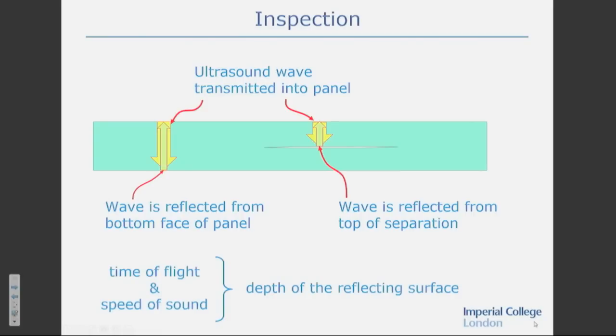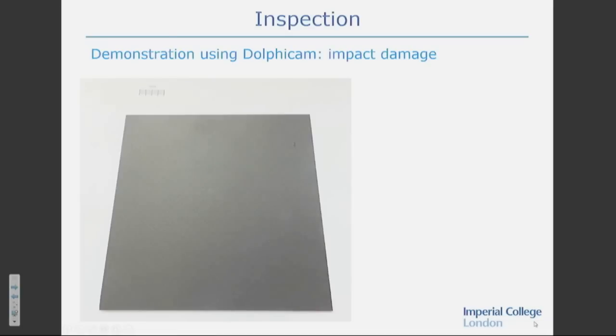We record the time of the signal to be transmitted from the top surface and received back at the top surface, and knowing the speed of sound in the material, we then know the depth to the reflecting surface. And clearly if that reflecting surface is less than the overall thickness of the laminate, we know we've got some problem inside our laminate. Now this is a laminate that I impacted.